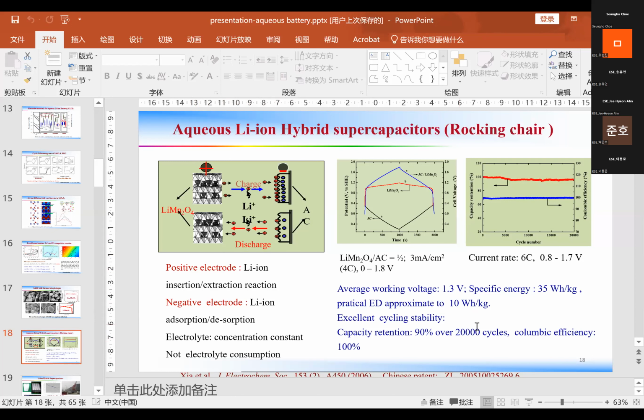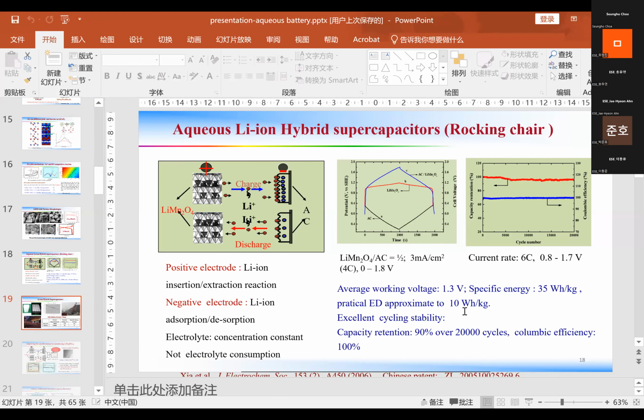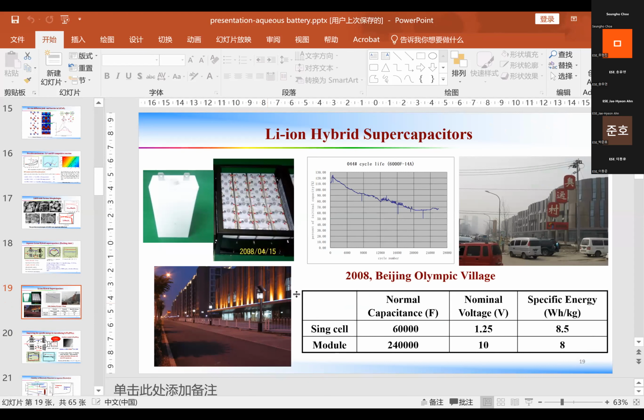So we get a good cycling stability over 20,000 cycles. These are laboratory cells, and we can get a specific energy of 35 watt-hours per kilogram. If we use a practical cell, it's about 10 watt-hours per kilogram. Then we cooperated with one Chinese company in Shanghai, a very famous company for supercapacitors. This is very early work. We did some hybrid supercapacitors, and this capacitor really can cycle over 20,000 cycles with capacity retention over 70%.